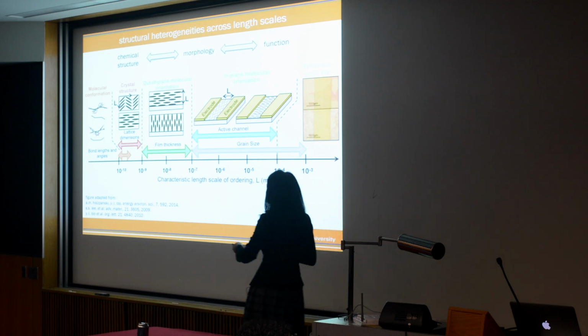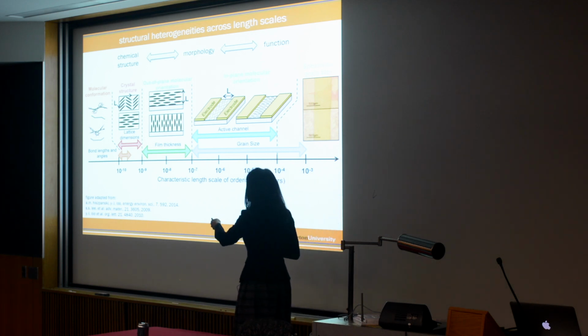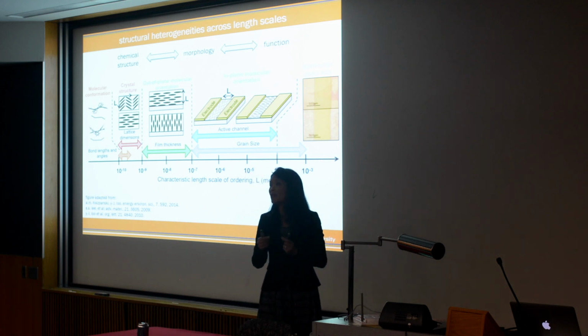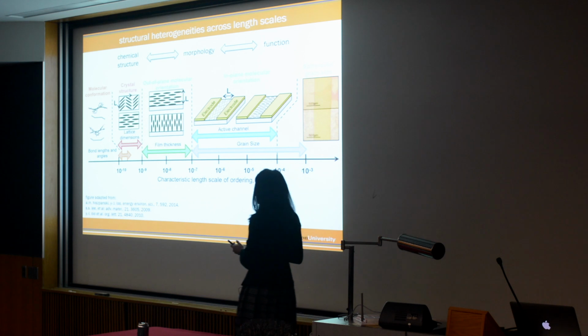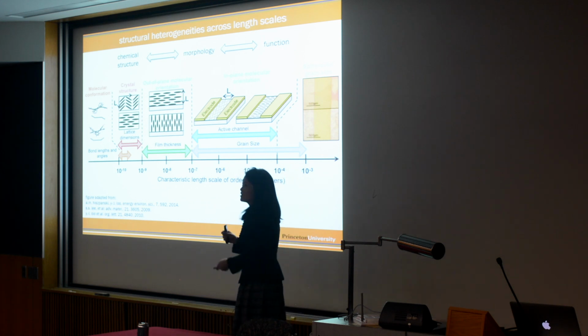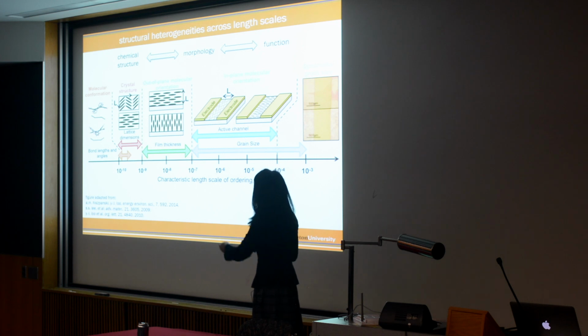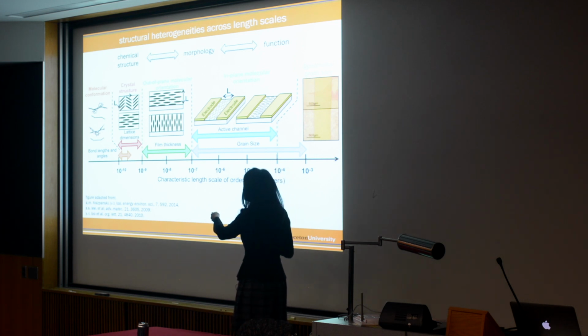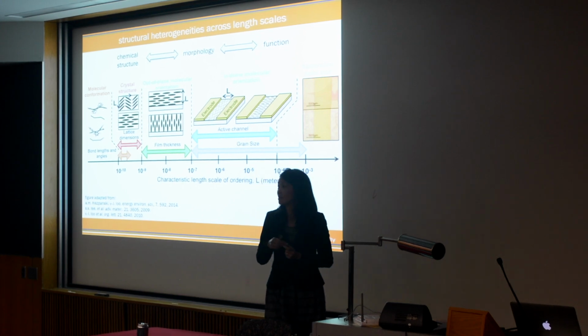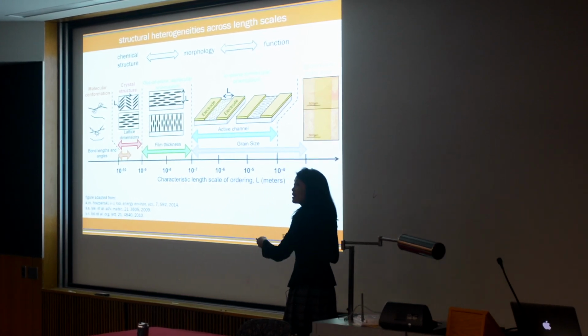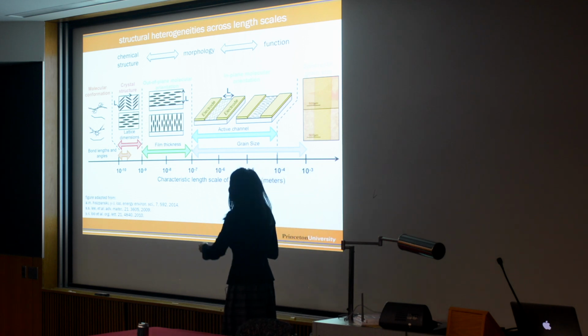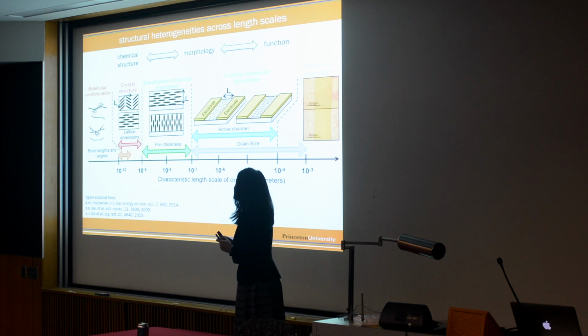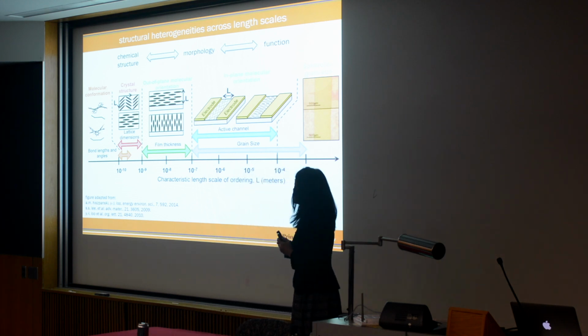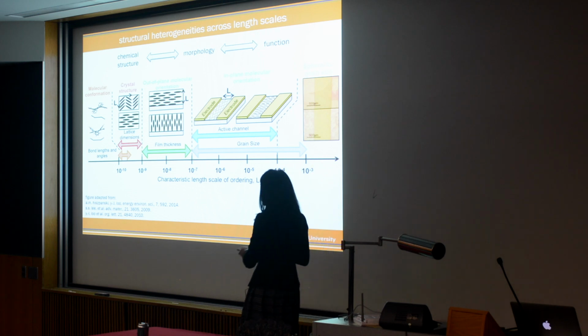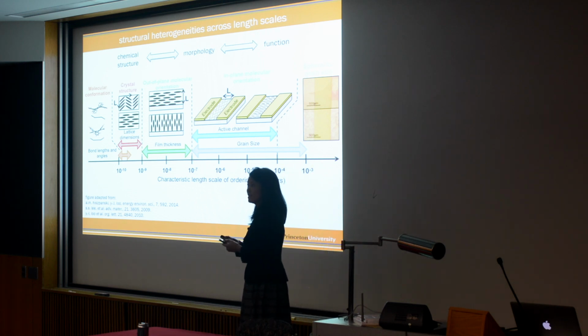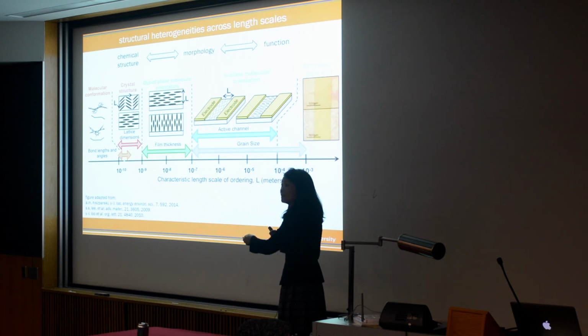But today what I'd like to focus on is really down at this scale, okay, at the molecular scale, looking at crystal structure. Given a molecule, the molecule can pack very differently. In this illustration, these molecules are illustrated with these black ovals. That's their pi plane. They can pack in a two-dimensional fashion, a brickwork fashion. They can pack in a one-dimensional fashion. And as you can imagine, depending on how they pack, that influences charge transport. So I'd like to talk about how you can have influence over these different packing motifs in these semiconductors. And this phenomenon is called polymorphism, meaning that a single molecule can adopt different kinds of packing structure.